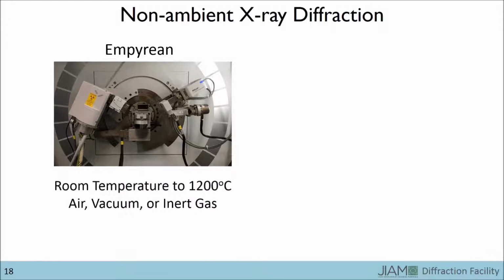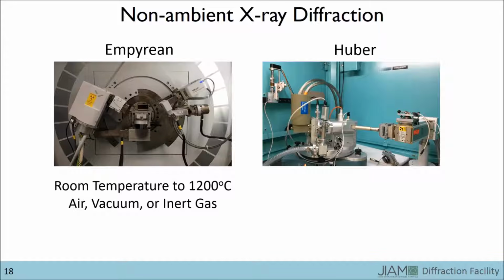The only difference between this next technique and the ones we have covered so far is that we are able to perform the diffraction experiments at non-ambient temperatures and environments. Our Empyrean diffractometer ranges from room temperature to 1200 degrees Celsius in air, vacuum, or inert gas environments, while our Huber diffractometer ranges from 10 Kelvin to room temperature in a vacuum environment.